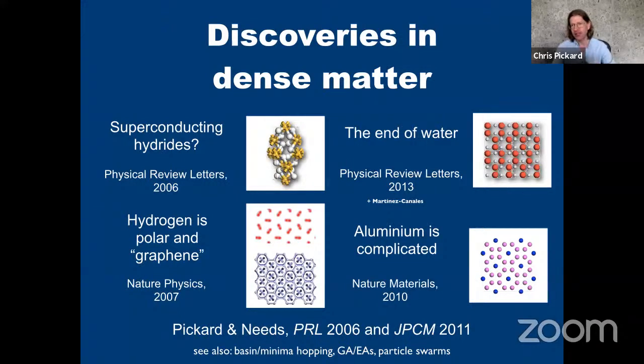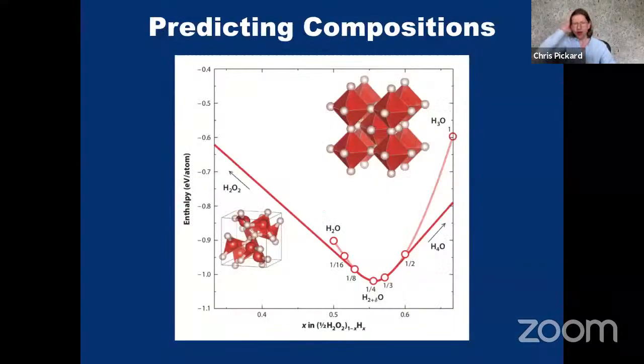You know, the breakthrough wasn't really structure prediction per se. This was being done before. It was really the marrying of these first principles methods with structure prediction techniques. And this has opened up a wide range of possibilities. Okay, so I mentioned the decomposition of water. The reason I want to mention this is that we're not just predicting crystal structures, we're also able to predict compositions. And that's crucial for these superconducting hydrides, because we don't know to start with what the ratio between the hydrogen and, say, silicon should be. In the case of silane, Neil Ashcroft just suggested silane because it was a known low pressure silicon hydrogen composition. But that's not guaranteed to be the most likely composition at very high pressures.